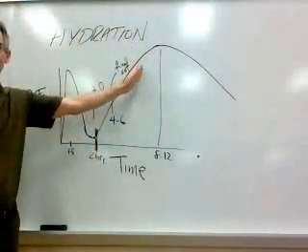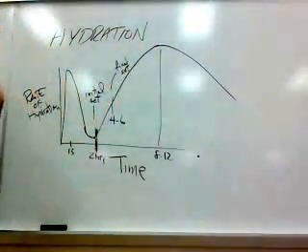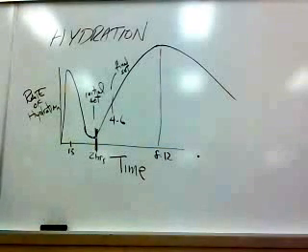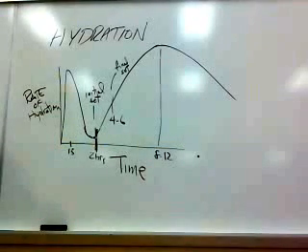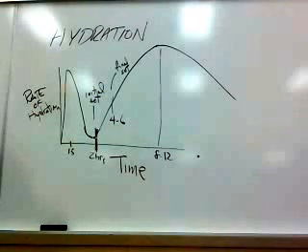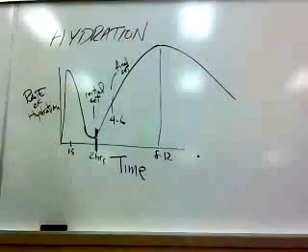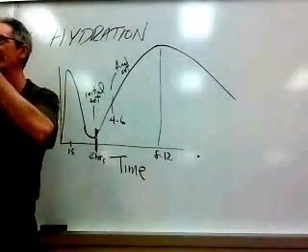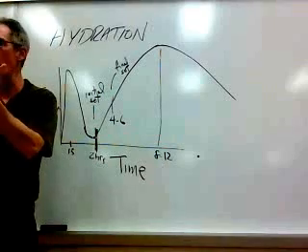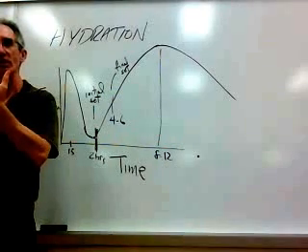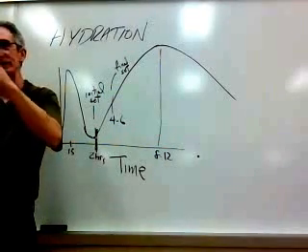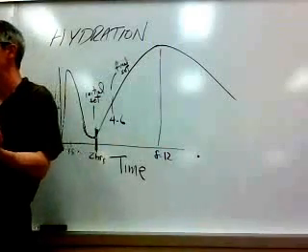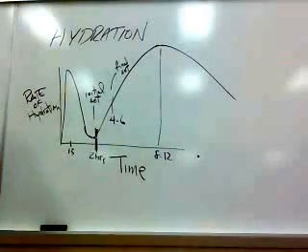The reason it does it here is all these ions that were flooding into the mix begin to form crystals. And that's how concrete gets hard. There's a crystalline matrix. There's several different types of crystals that are created that actually begin to grow and form and put their arms around the aggregate and bind them together.